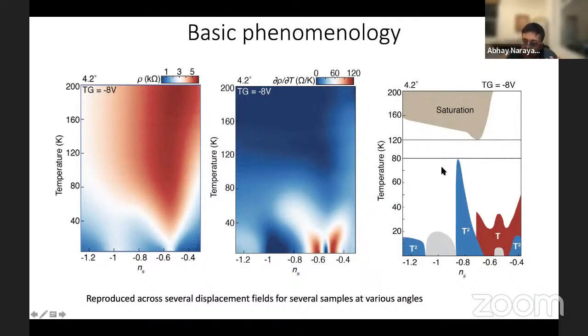And what emerges is that there are two what look like quantum critical fans of T-linear behavior, which project to the metal to insulator transitions on either side of the insulator. And so this very much looks like quantum critical points on either side of the insulator.